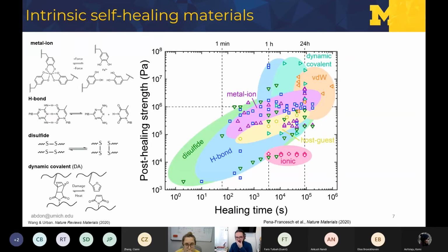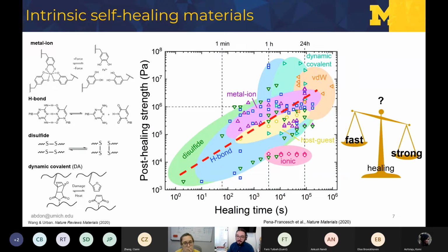But this has a problem, right? We can see here on the left several different examples of intrinsic healing chemistries through hydrogen bonding, through disulfide bonds, etc. But a common challenge to these materials is that if we look at this graph that plots the healing strength versus the healing time, we see that there's a fundamental trade-off between those, right? This comes from the fact that if we want fast healing, you need high chain diffusion and high chain mobility, which comes at the cost of stiffness in your material, right? So this leaves this region over here, of fast and strong healing, quite unexplored.